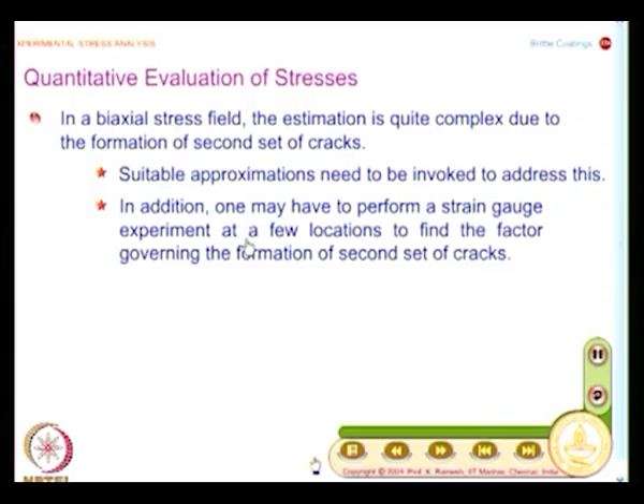Because in the initial case what we say is the coating is unperforated, I have a uniform coating, and the coating being a brittle material, it may fail by maximum stress theory or maximum strain theory, whatever the theory that you want to have, then the cracks form. But if you want to analyze the formation of the second set of cracks, you do not have a uniform coating, you have a coating with cracks. So, that is why you need to bring in an additional approximation, and you have to say there must be some kind of a factor which governs, which may not happen at the actual failure strain of the coating, and that factor has to be determined experimentally. You need to make an additional experiment using strain gauges, otherwise you will not be in a position to do it.